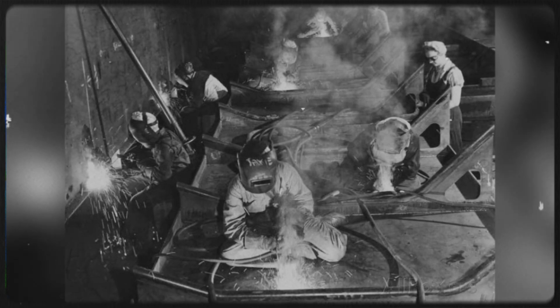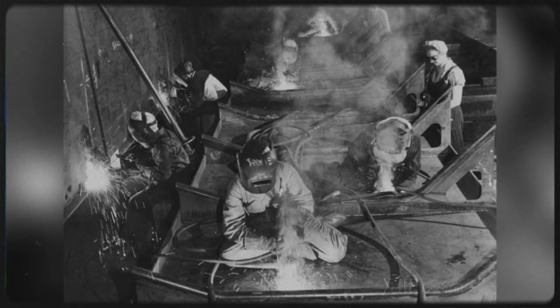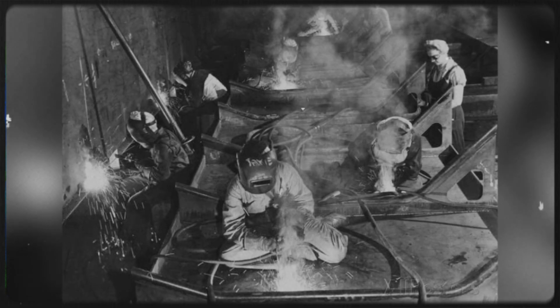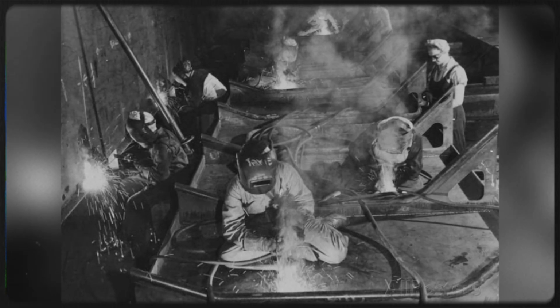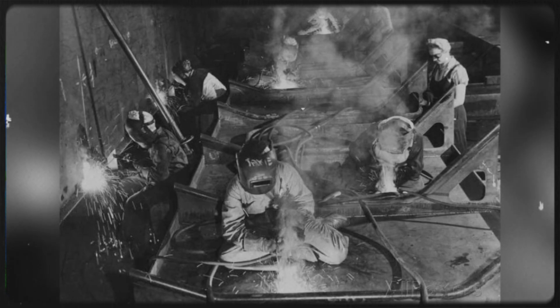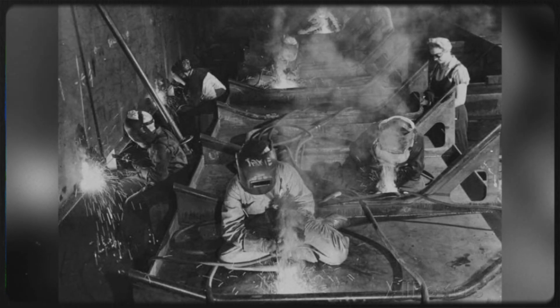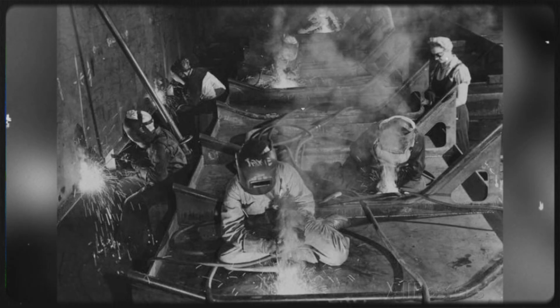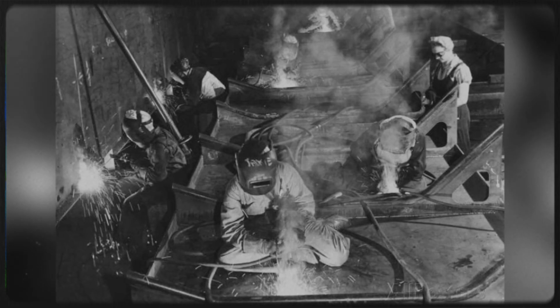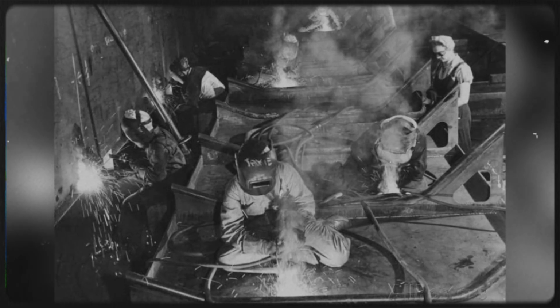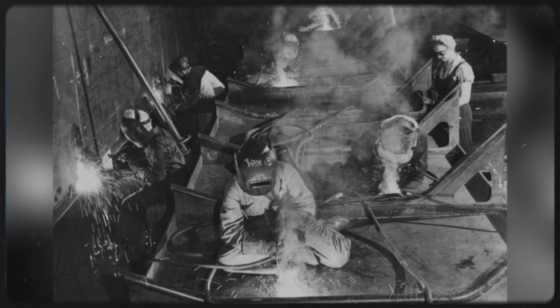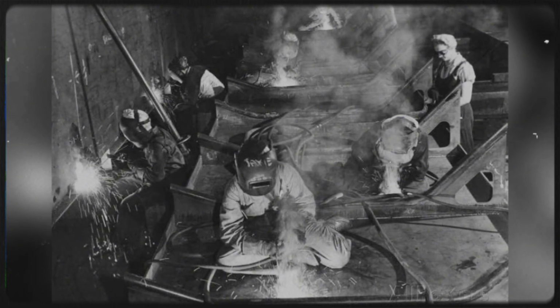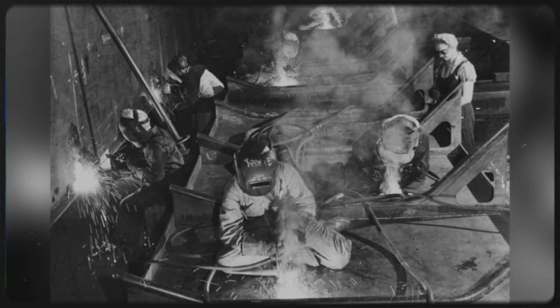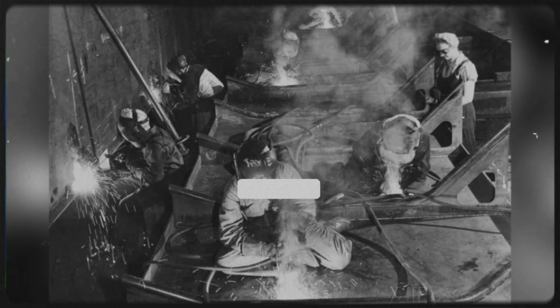He grabbed a ball-peen hammer from his tool belt and tapped the hull plate lightly, listening. The sound that came back was wrong. Not the solid ring of continuous steel, but something slightly hollow, slightly off. He tapped again, 6 inches to the left, and heard it again. By 1:30 in the morning, he'd tapped his way along 40 feet of hull plating on 3 different frames, and the sound was wrong everywhere he checked.